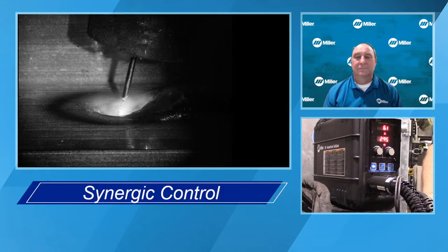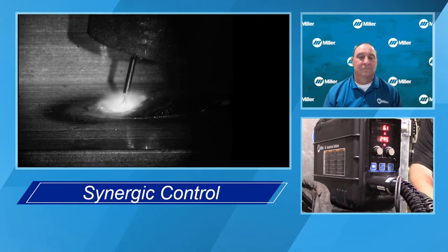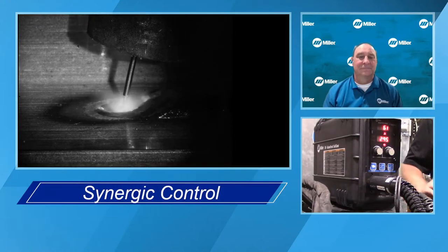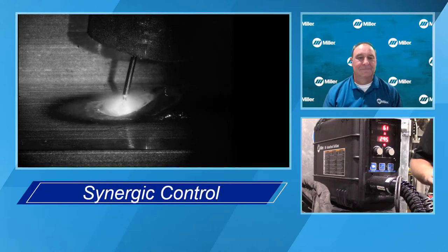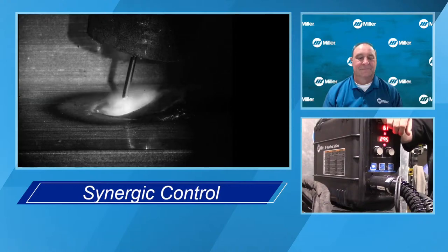Now, the benefit of synergic is when we run synergic, as that wire speed changes, the arc length does not change. If you watched that video as it was going across the screen, that wire feed speed is going from the low end, around 180 amps, and then we're gradually increasing it. You can see that arc length is not changing at all. It's staying pretty close. You can see that puddle's getting bigger, that crater's getting deeper, getting more fluid. The puddle's building up higher behind it.